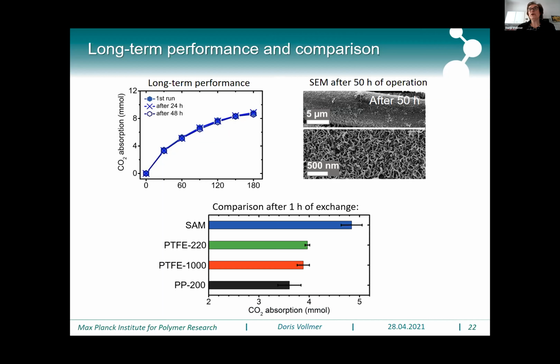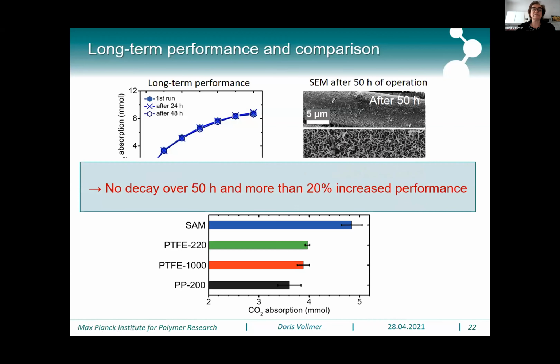Then we were able to compare our results with the superamphiphobic membranes to the conventional membranes. After 1 hour of exchange, we had an increase of carbon dioxide uptake by approximately 20% compared to the conventional membranes. And apart from this 20% uptake increase, we did not observe a decay over 50 hours.